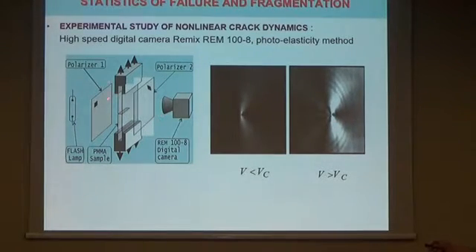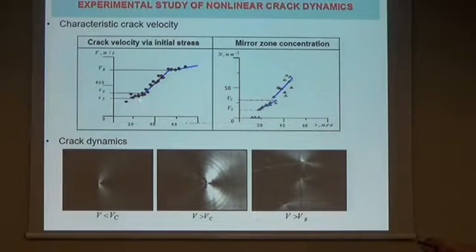But for this goal, using our experimental setup, we reformulated the experimental program, and we combined J. Fineberg's dynamics of crack propagation with high-speed imaging in polarization schemes, which allowed us to confirm the critical velocity found by Fineberg, but also to find another critical velocity, where we have transition from steady crack propagation to the branching region, and then to this branch that exactly corresponds to dynamic branching in spall. In this case, when we go to this branch, you have very pronounced branching where the daughter crack practically forgets about the crack that originated this scenario.